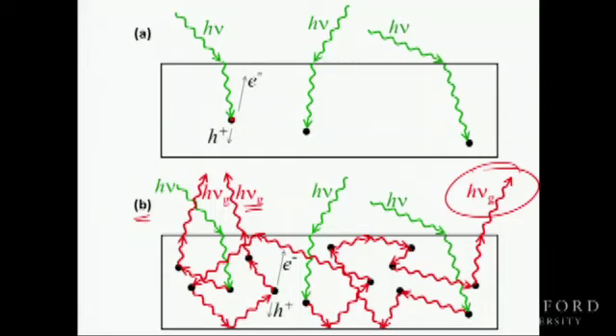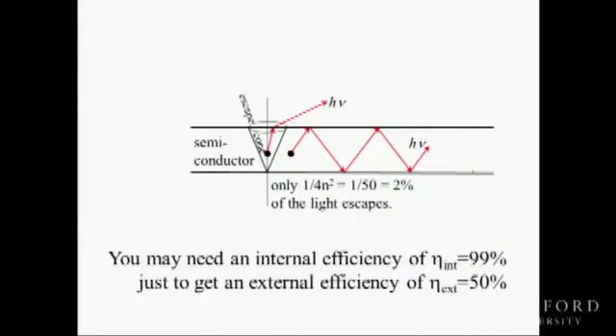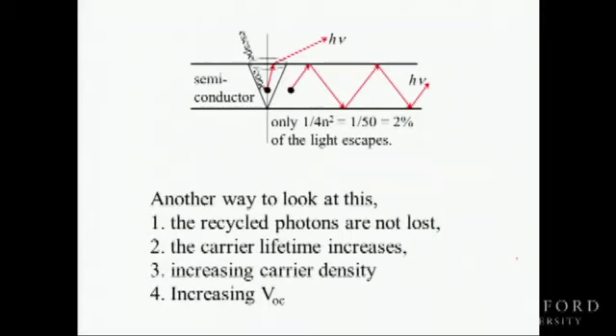Well, now, why is this a vexing problem? Well, because you're going to bounce around many, many times, you might even get absorbed, re-emitted, and so forth, you might need an internal efficiency of 99%, even to have a 50% chance of getting out. And so this puts a tremendous burden on the internal efficiency of the material. And this is why nobody has really broken the 25% barrier until now.